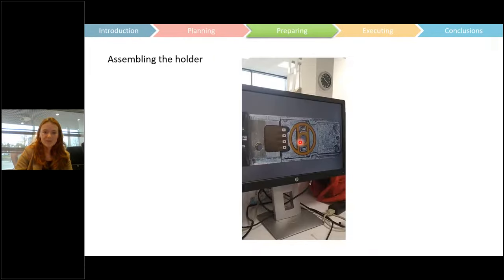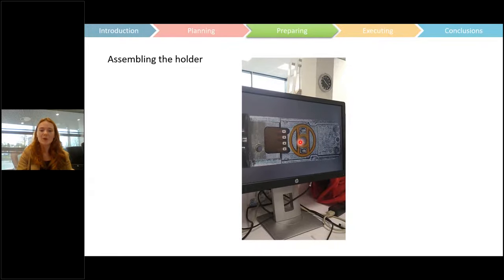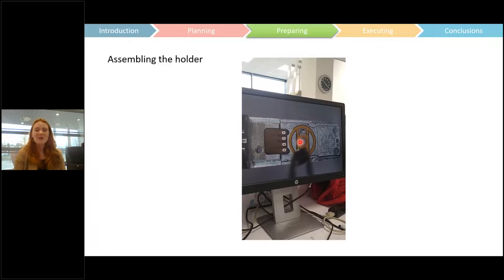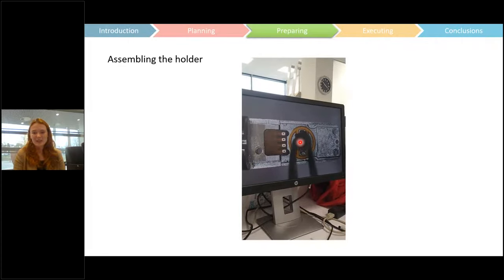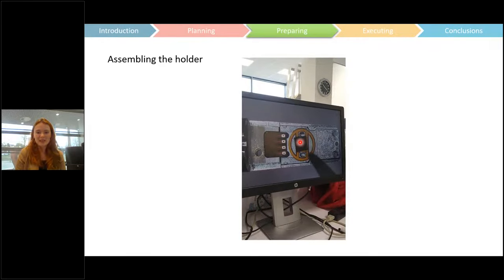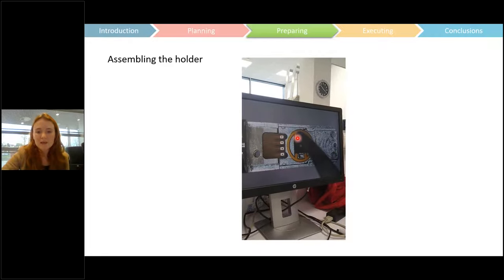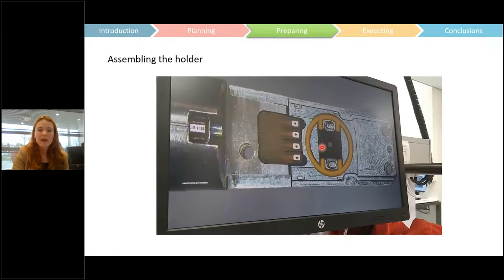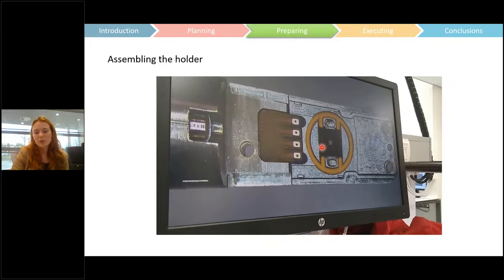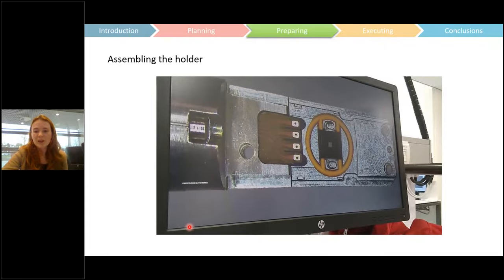And so for assembling the holder, again, not going to go into too much depth, but you would put your little chip on first. When you do this, it's really important to make sure it's tucked nicely under the O-ring. So as you slide it in, it really helps. I really hope that I had good solid hands in this particular movie. It really helps to give it a good press on the sides and just tuck it in and make sure it's really securely being held, because that can be a source of broken chips. And then you would put your top chip on.